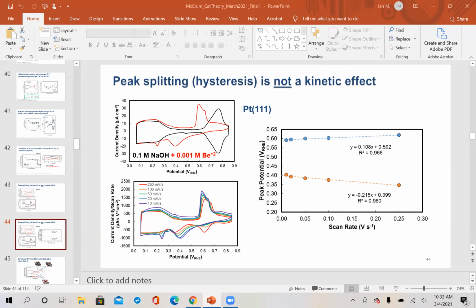And maybe I'll briefly add, hydrogen and hydroxide can adsorb to a pretty wide range of coverage on platinum. All of the cation coverages we've looked at are up to 1/3 of a monolayer. I think that's the highest cation coverage we look at, maybe slightly higher than that. I think we've gone up to 0.5 of a monolayer along the step. Because the cations retain most of their charge on adsorption, for all of the cations, they show very strongly repulsive interactions on the surface. And so that puts a hard limit on the favorability of adsorption with increasing coverage. So we see a strong coverage dependence, a repulsive interaction in the adsorption of the cations.